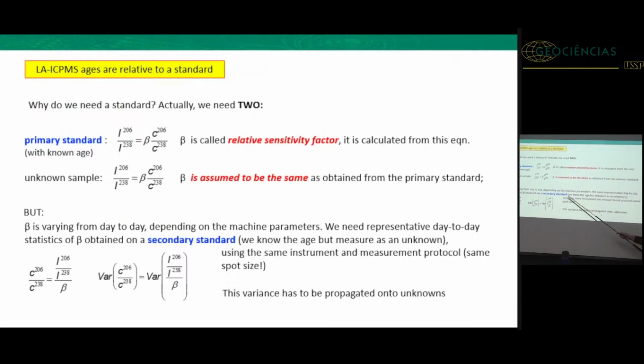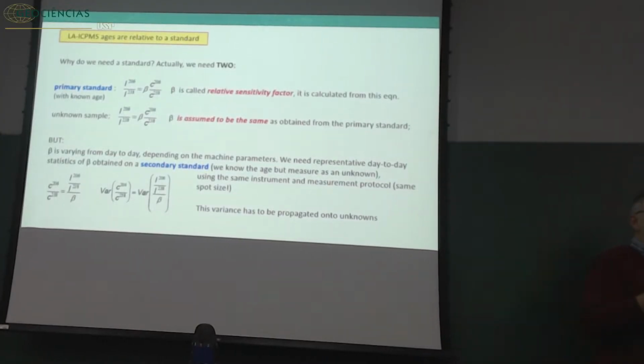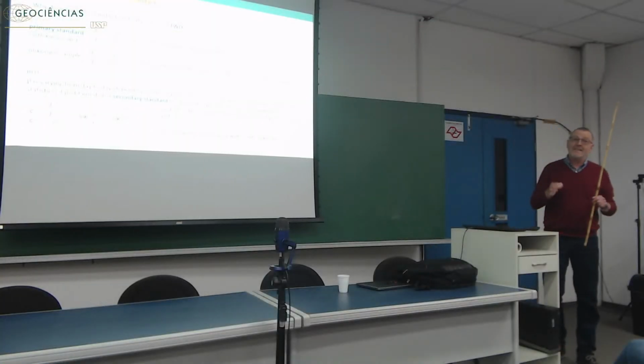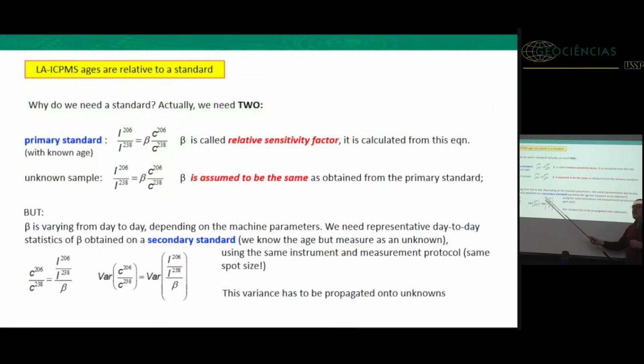There are several problems with this. The beta is varying from day to day, depending on machine parameters. Sometimes we don't know, depending on the weather, temperature, the mood of the lab technician. But we need to have representative day-to-day statistics of beta. And this we do by using a secondary standard. Again, a reference material. We know exactly how old it is from an ID-TIMS age. I only accept ID-TIMS ages, right? Because we need this then to determine how much this beta is varying per day or between 2 sessions or between 4 sessions. And this variance of this beta has to somehow be propagated onto our unknowns, somehow, which is not trivial at all.